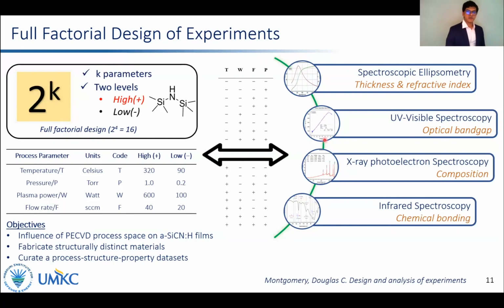While doing this, we acquired several properties of the thin films, like thickness and refractive index from spectroscopic ellipsometry, optical band gap from UV visible spectroscopy, composition from XPS, and chemical bonding information from FTIR.